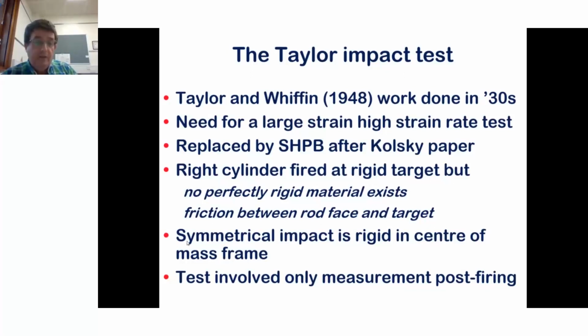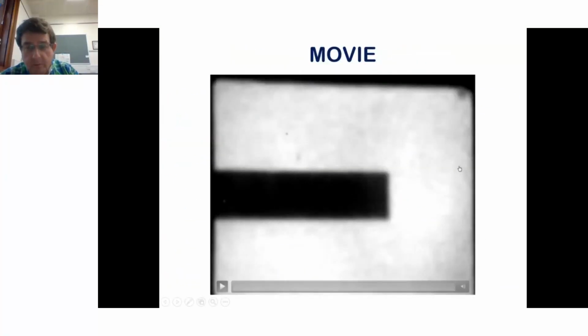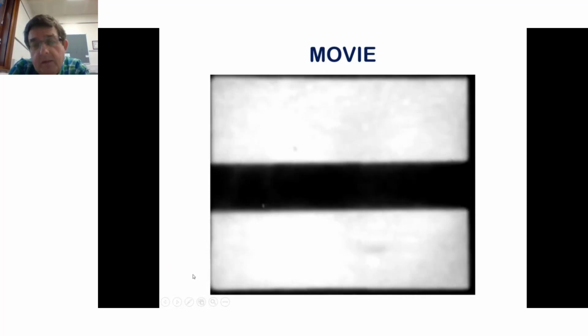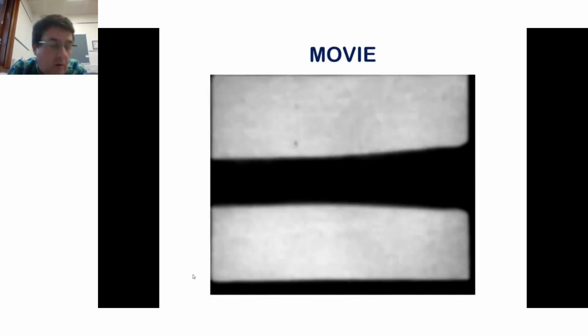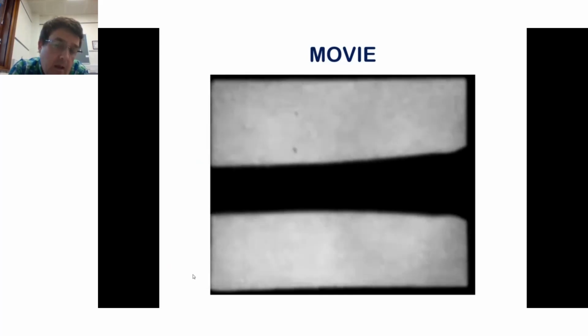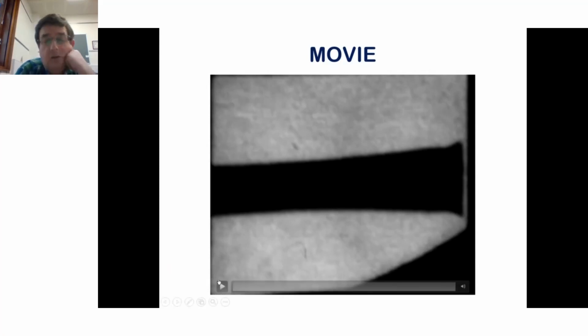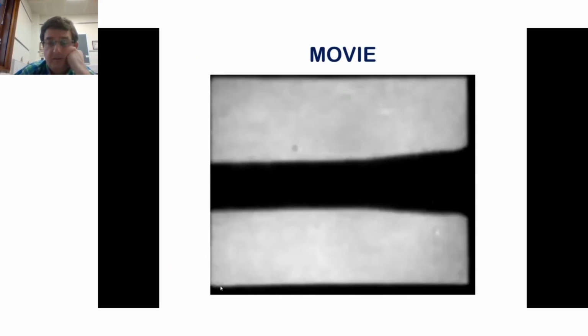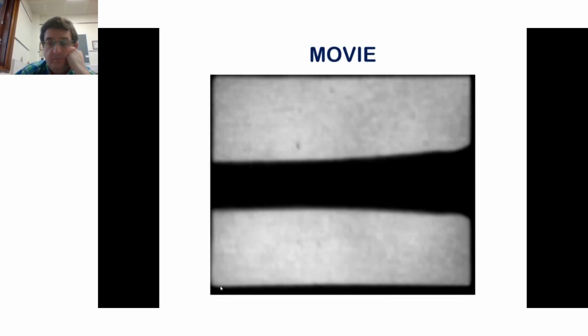And it involved firing a cylinder at a rigid target. So let's have a look at what the experiment looks like. On this side of the screen here, we have a rigid target, and this is a rod that's being fired at that target, at about 100 meters a second. So the rod goes up to the target, impacts it, and deforms on the surface, and then eventually it bounces off. So I'll play that again. This is the impact of, in this case, a copper rod on the surface of the material. Okay, there it is. Fairly straightforward, I hope.